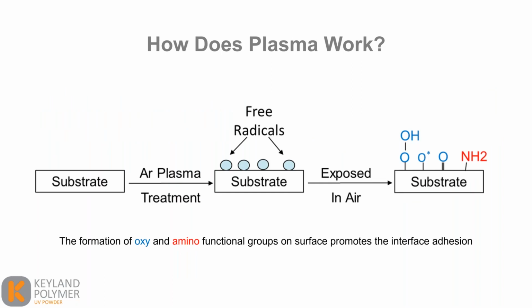So this newly formed plasma affects the substrate by bombardment and also by forming oxy and amino functional groups on the surface. And these promote interface adhesion, and they remove organic contaminants, mold release agents, and those sorts of materials.